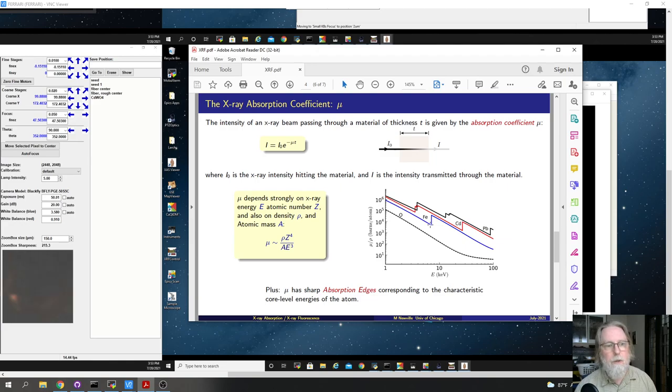First of all, you can go above and below the edge to get differential absorption to distinguish whether that's iron or not. You can also zoom in on that and look at the fine structure of that absorption edge and get interesting properties about the chemical state of the element. That is, the X-ray has to go into the continuum or into the just unbound, anti-bonding states. And so that can be affected by the local coordination, the chemistry of that atom. So looking at those edges in detail will give different spectra that easily distinguish iron metal from iron 2+ from iron 3+, and so on. So in fact, in our beamline, most of what we do is a coupling of X-ray fluorescence and X-ray absorption.